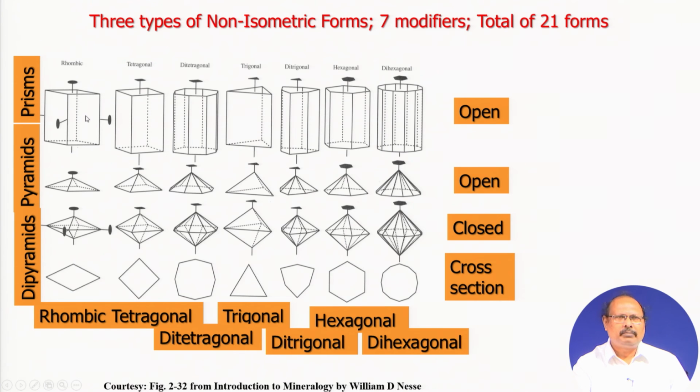Now, this is a rhombic prism here. So, there are 4 faces here, and this is present in an orthorhombic crystal system with the point group of symmetry 2, 2, 2. All 4 faces intersect along this line, and this is parallel to this vertical dyad here. Now, if you see here, in this case the vertical axis is a tetrad axis or 4-fold axis of symmetry, and you have here 4 faces, 1, 2, 3, 4. That is why we call it a tetragonal prism here.